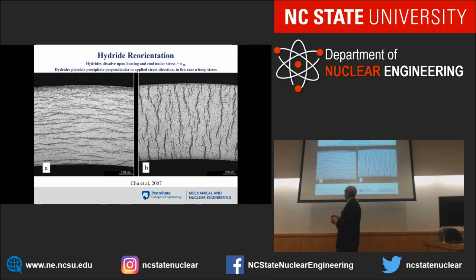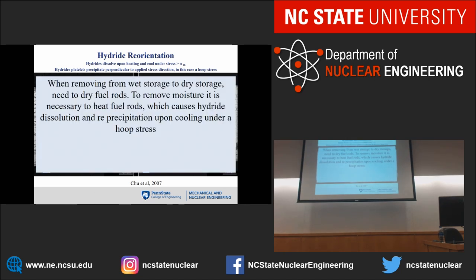Okay, so when removing fuel from wet storage to dry storage, you need to dry the fuel rod. You don't want the water in there. So to remove the moisture, it's necessary to heat the fuel rods. This causes all the hydrides that are precipitated to dissolve. When they reprecipitate again, they're going to reprecipitate under stress, because the temperature is high and I have fission gases inside my clad, and now there's going to be a hoop stress.